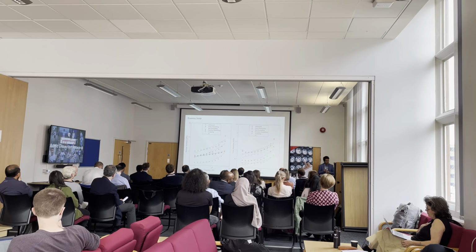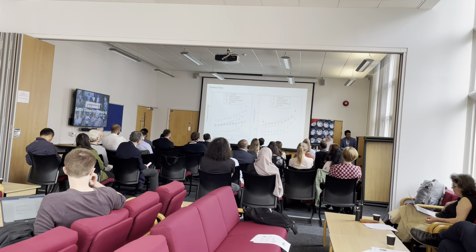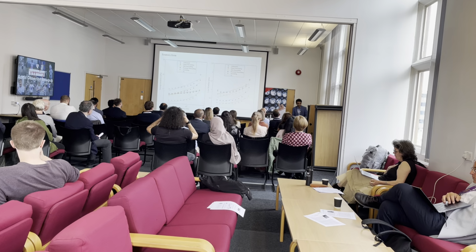So you can see this figure here. This is the storage modulus as a function of frequency from 0.1 until 5 Hz, and also the loss modulus. You can see a very smooth behavior across different regions of the aorta. And this model was able to fit all the regions of the aorta with a correlation higher than 0.99. So that's something which is good.